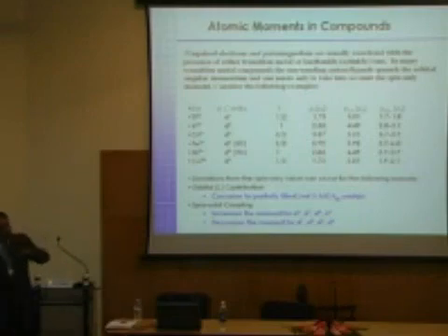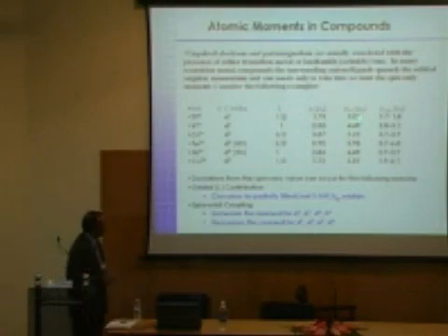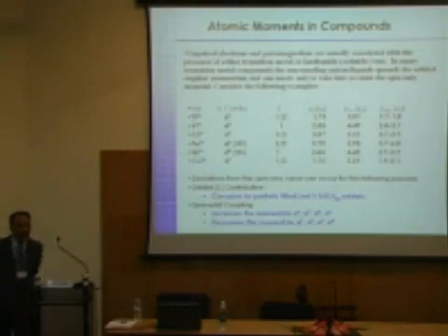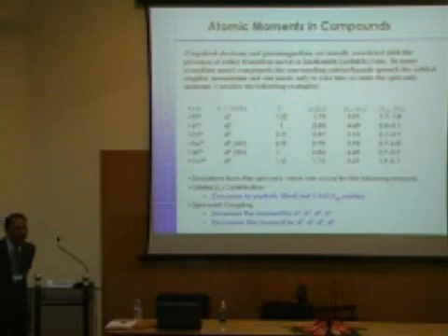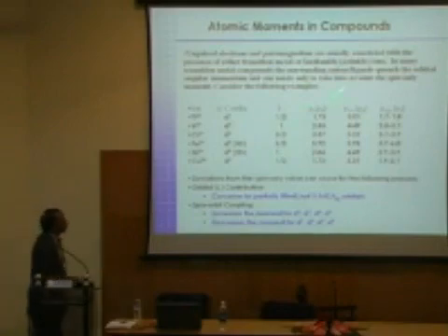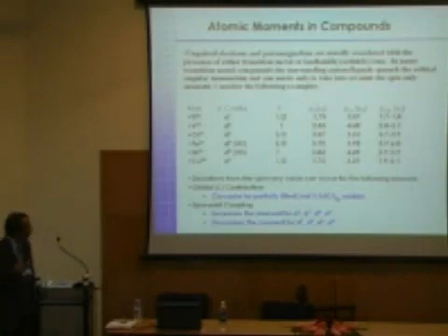But if you also assume the orbital contributions plus the spin contributions, the total comes to about 3.01. But experimentally, titanium 3+ always gives magnetic moments in the range of 1.7 to 1.8. So what does that tell us? Does the orbital moment contribute to the magnetism or no? No. So clearly I see one head saying no. Yes, in the case of titanium, the magnetism is purely the spin contribution only. There is not much of magnetic contribution from the orbits.